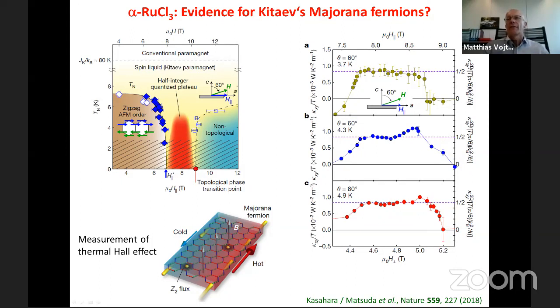Now, this here could simply be a red herring. So in other words, this can by accident lie in the vicinity of 1/2 and mean nothing. I mean, the error bars are not small, and it's not very close to 1/2. But there is no good explanation as to why it should be close to 1/2 if it's not a Majorana edge mode. So in this sense, I still consider the Majorana edge mode as the most plausible explanation. And there is none which, apart from saying, oh, it's an accident, would rationalize this result.